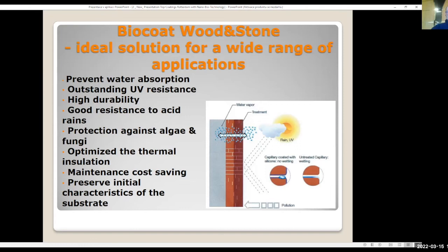It is also important to notice that some special materials have a special accumulation. Stone and concrete reach 63 degrees, although the outside temperature is not so high, because they accumulate the heat. The same is the metal. Metal accumulates the temperature up to 72 degrees. And we cannot do anything else, only make some coating.